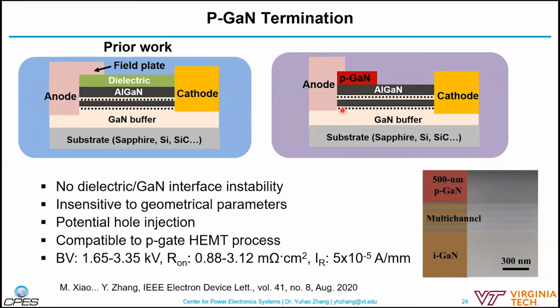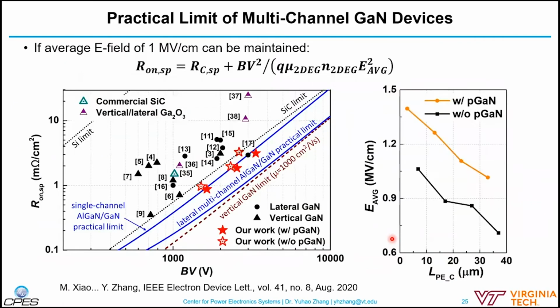So we made this structure and demonstrated a breakdown voltage of over 3.3 kV, with a pretty good specific on-resistance and leakage current in the 10 to the -5 amps. A very interesting thing after we demonstrated these devices is that we can now calculate the practical limit of these lateral devices, which is the trade-off between the specific on-resistance and breakdown voltage. If we can manage the electric field very well and achieve an average electric field between the anode and the cathode, or in the transistor, for example, between the gate and the drain, of about 1 megavolt per centimeter, then you see the